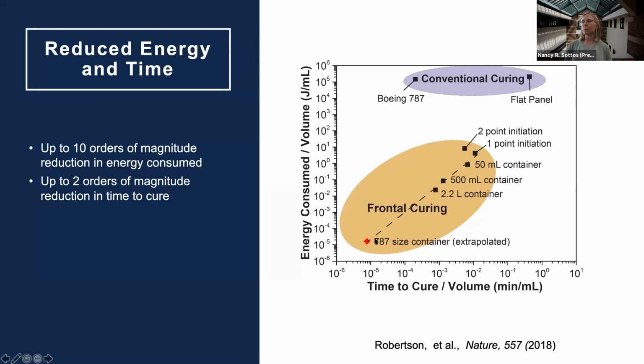This is an extrapolated point for a 787 size container. And that's what lets us make this conjecture that there's really a possibility of up to 10 orders of magnitude reduction in energy for a large structure like a 787 fuselage, and over 2 orders of magnitude reduction in the time it takes to cure such a size part.